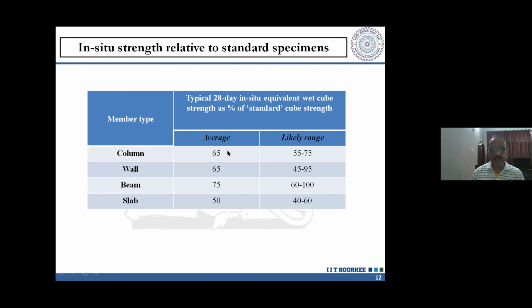And because of that, an interesting thing is that you can see what the variation is. The typical 28 days in situ equivalent wet cube strength as a percentage of standard cube strength could be in the range of 55 to 75% in a column. In a wall, it could be 45 to 95%. This is generally seen in a well-built column. It is not because there is some poor quality of construction. It is happening because of natural, automatic reasons.